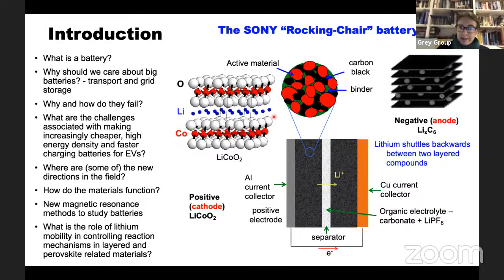Anyway, so the rocking chair battery, or the Sony rocking chair, that really is in all of your mobile phones, was originally put together in 1991 by Sony, and it was called a rocking chair battery because the lithium ions go backwards and forwards between lithium cobalt oxide and graphite. And so on oxidation, you oxidize the cobalt 3+ to 4+, and you pull the lithiums out. They go through a non-aqueous electrolyte, and then they get nominally intercalated safely into these graphitic anodes.